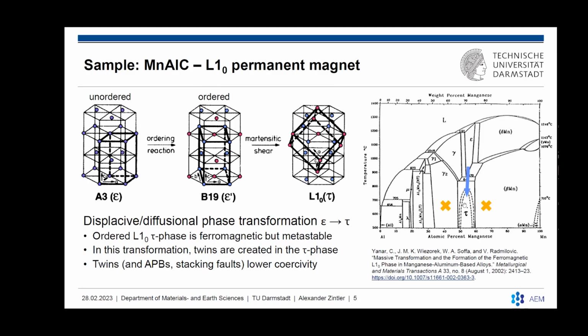So what you start off with in the beginning, you start from the melt and you quench the melt in the correct composition to the epsilon phase. And that epsilon phase just has a random distribution of the manganese and aluminum atoms in the crystal structure. And then by a very, very careful annealing step, you will actually go from the epsilon phase to the tau phase to gain the magnetic properties. And this careful annealing step can be done in different ways.